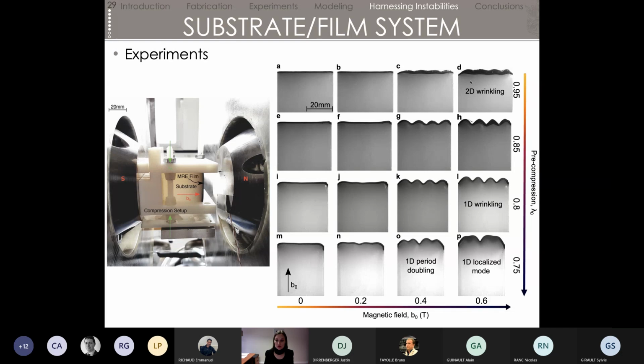And then at some point, what we noticed also is that if we compress too much, we can already see a small instability on the sample even before applying the magnetic field. And then we go to more exotic profiles, which are post-instabilities or post-bifurcation, called period doubling or localization. So I'll come back on that after for those who know a little bit about these classical shapes.